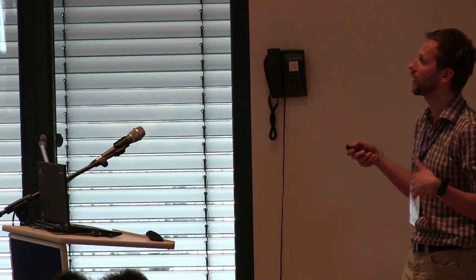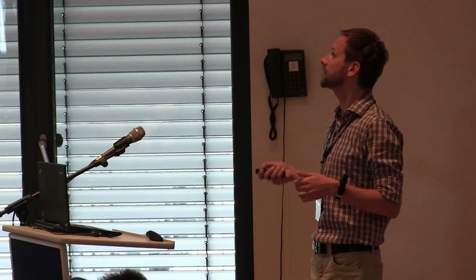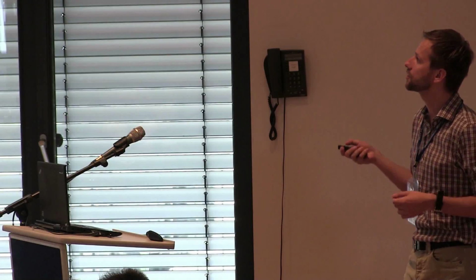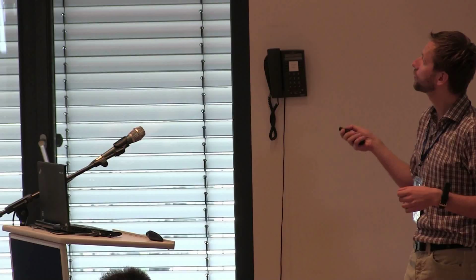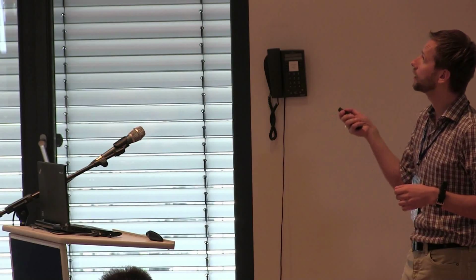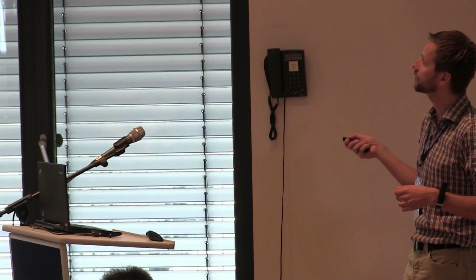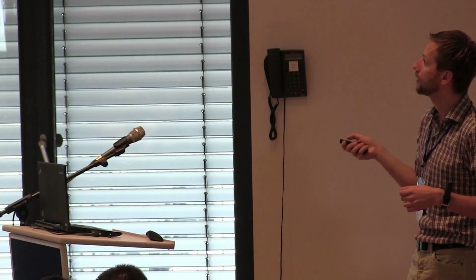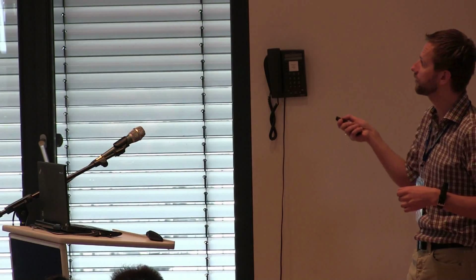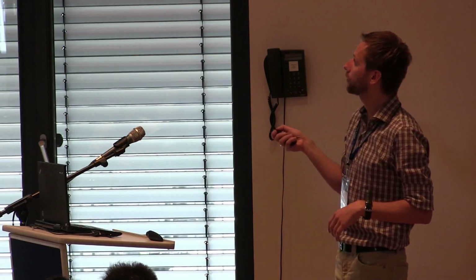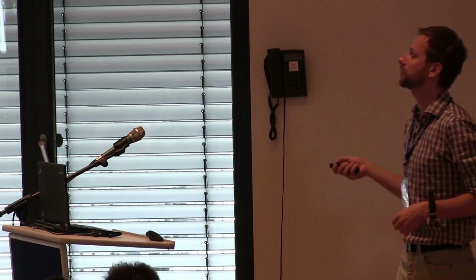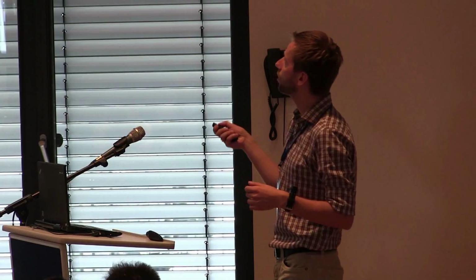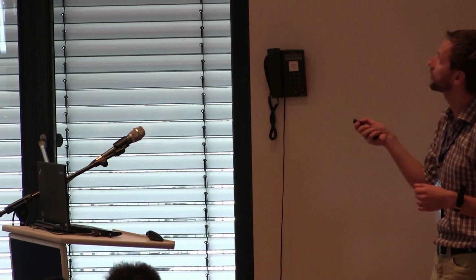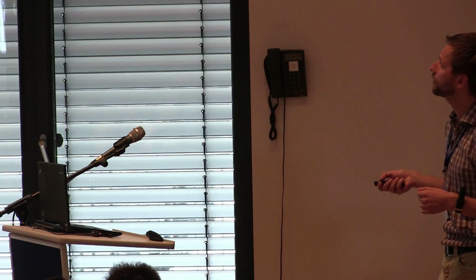So in this experiment, we had access to all interesting field regimes, from the weak field, which is the linear regime, to strong fields, which is typical for transistor, about 100 kilovolts per centimeter. And also, if you Fourier transform the Terahertz waveform, then this is the frequency spectrum. And within one spectrum, you have the frequencies of the present generation of transistors, about 400 gigahertz, and also the target frequency for the industry, and the frequencies exceeding 1 terahertz. So we can measure all of that in one go, just by measuring these transmitted waveforms. All right, so without long ado, this is the result.